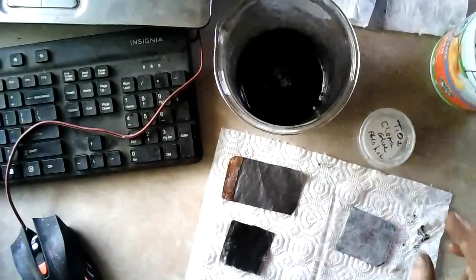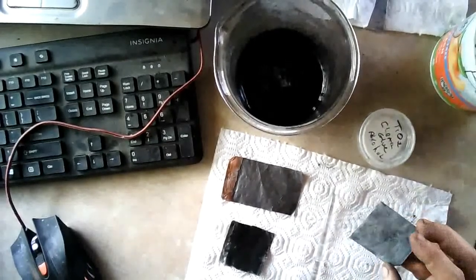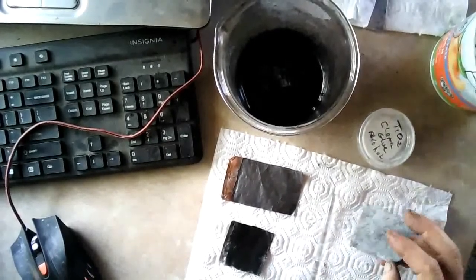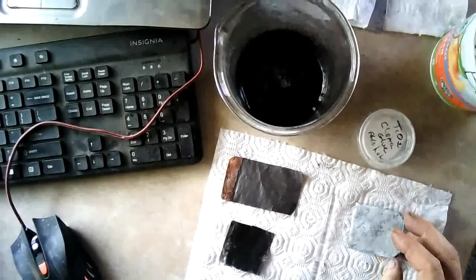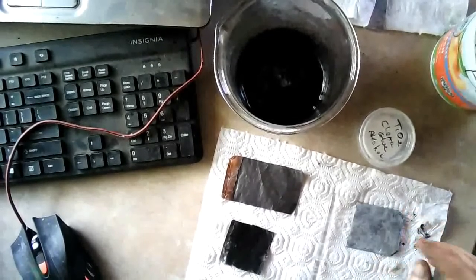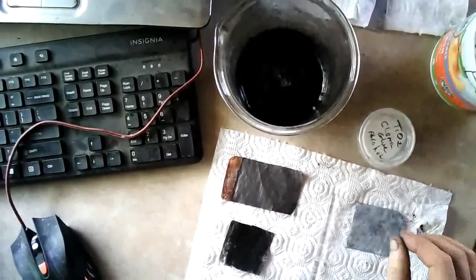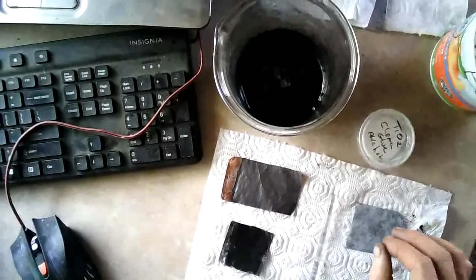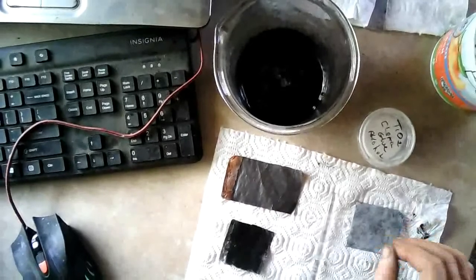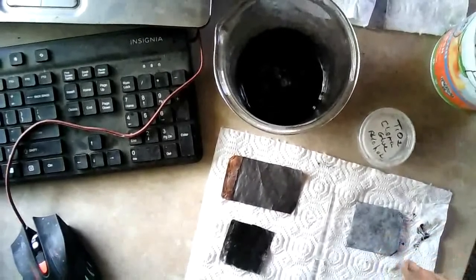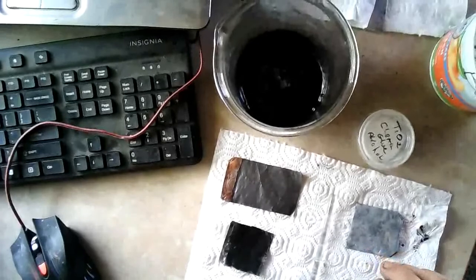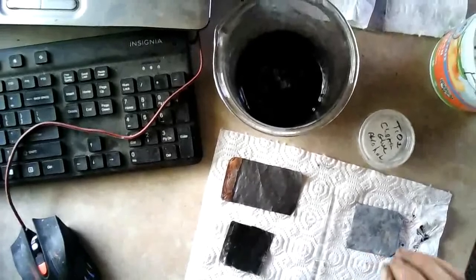But instead of dipping it in a mixture of borax and trisodium phosphate, I just dipped it into straight borax. If you dip it into just straight borax, you get a soft gel thin film. If you dip it into trisodium phosphate by itself, you get a soft thin gel film.